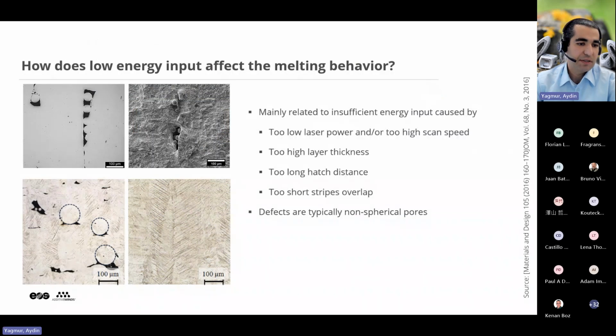If the process is not optimized or some interference or problems occur, what will happen? If the laser energy is not absorbed by the material in an optimized way, we observe the formation of volume defects, so-called lack of fusion defects, which are very dangerous, damaging the material properties because of the shape with notches inside. Lack of fusion defects are not desired, and are not accepted in additive manufacturing.